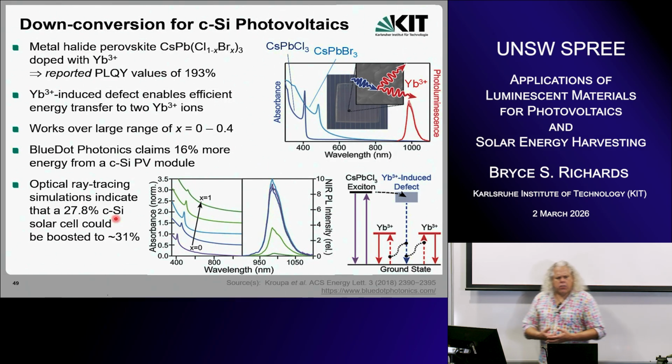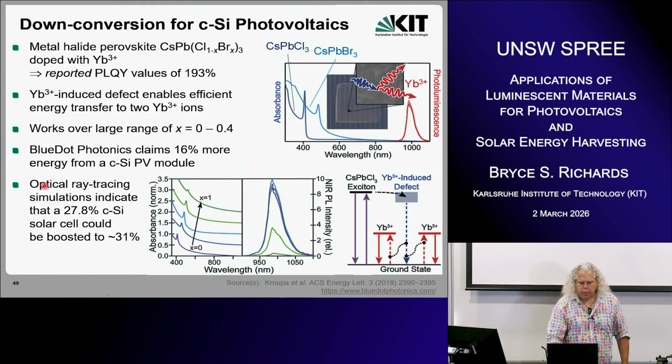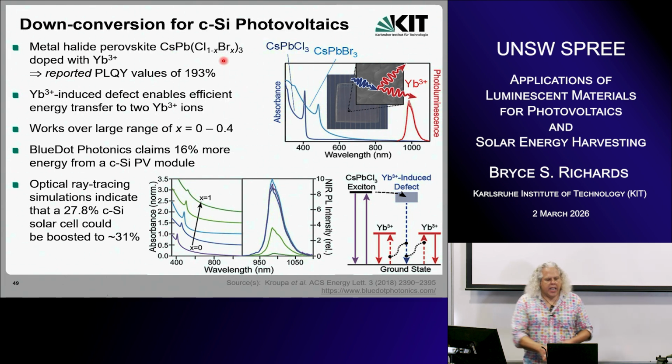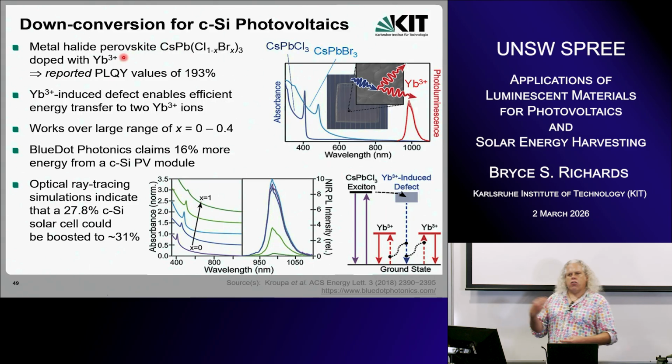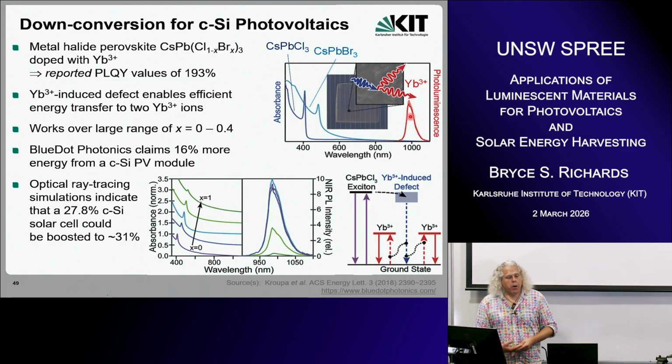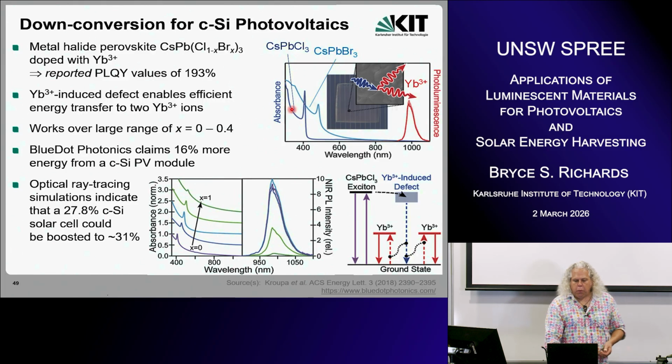And then in about 2017, 2018, the Gamelin group in Washington in the US published this material system based on a perovskite, which some people here in the room working on perovskites might recognize, cesium lead chloride or bromide, and again, doped with ytterbium. The ytterbium is there for the same reason I said last time. This should be a nice emitter out at about 980 or 1,000 nanometers. This luminescence is well absorbed by the silicon. And the absorption, because it's a semiconductor, this should be quite strong.